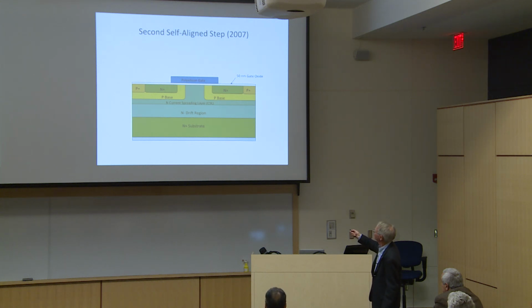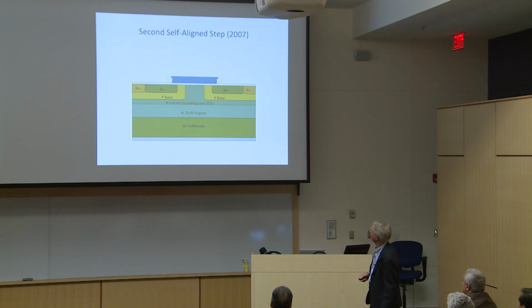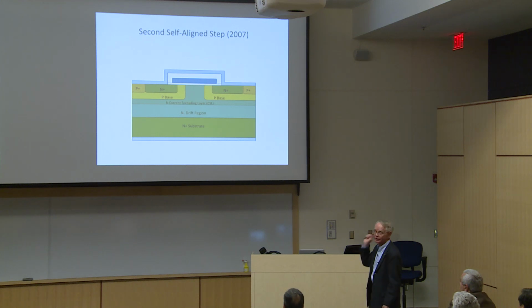So what we did in that process was we put a fairly thick polysilicon gate, and after we'd done all the other processing, we oxidized that. So it's now completely surrounded with an insulator. We do a light etch, just a very thin, short etch. This is a much thinner oxide, and we can remove that oxide without really taking off all of that. We now put a nickel metal right over everything, and it doesn't contact the gate because the gate's now insulated.